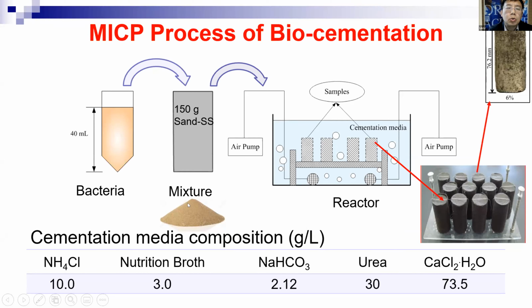The original is loose material, but once you have this precipitated calcium carbonate, it can bond the sand particles together. For this reaction, I just reacted for 7 days. You can keep going for 28 days. But in the first 3 days, the bacteria are really active. After that, the bacteria are covered by the calcium carbonate, so their activity goes down. After 7 days, we stop the air pump and take the sample out.